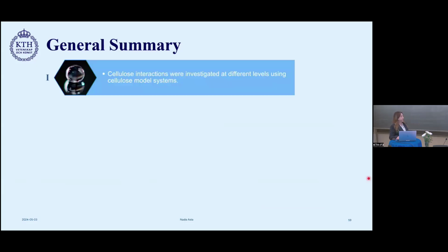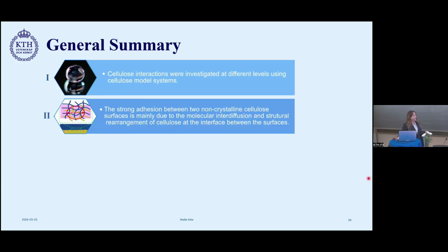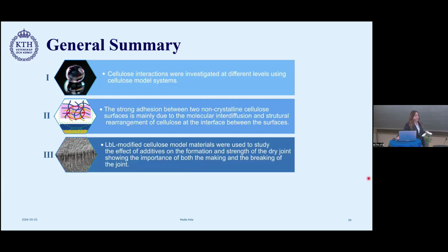So as a general summary, cellulose interactions were investigated at different levels using cellulose model systems. The strong adhesion between two non-crystalline cellulose surfaces is mainly due to the molecular interdiffusion and structural rearrangement of cellulose at the interface between the surfaces. LBL-modified materials were used to study the effect of additives on the formation and strength of the dry joints, showing the importance of both the making and the breaking of the joints.